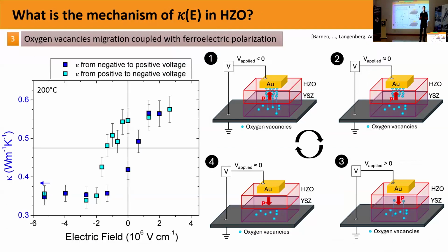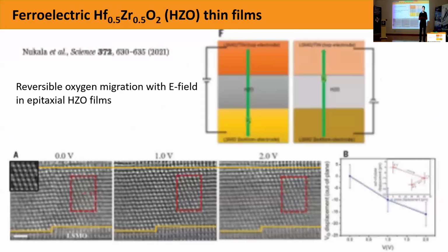So the thing is, the concentration is too low to be seen by scanning transmission electron microscopy, or at least we couldn't see it. But the theoretical calculations, actually, this is the experimental results. It was a theory here in the group that we computed the number of vacancies that can reproduce the results of thermal conductivity of our hafnium zirconium oxide, and it was quite low. The concentration is enough to scatter phonons and to reduce the thermal conductivity. We couldn't see it in electron microscopy.